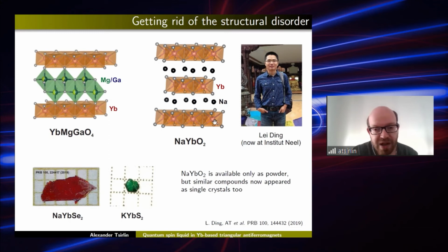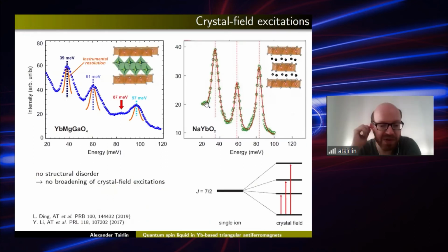So this part of the work I really owe to Lei Ding, who was at some point a postdoc with us, then later at Oak Ridge, and now he's working at Institut Néel in Grenoble. I should also say that after this was published, we did quite a lot on the similar sulfide and selenide compounds, which can be prepared as single crystals in contrast to this oxide. But today, let me tell you more about the oxide, because the sulfides and selenides work is still a bit of a work in progress, but for the oxide, we understand quite well what is going on.